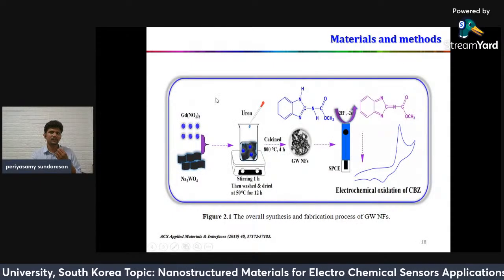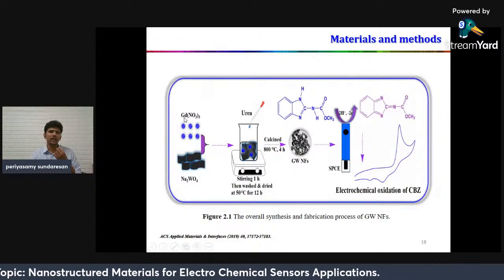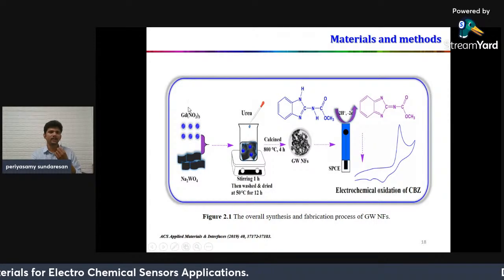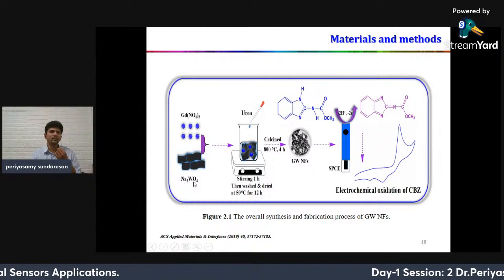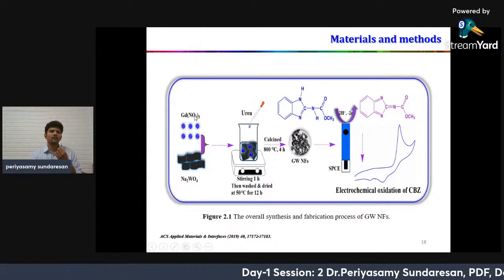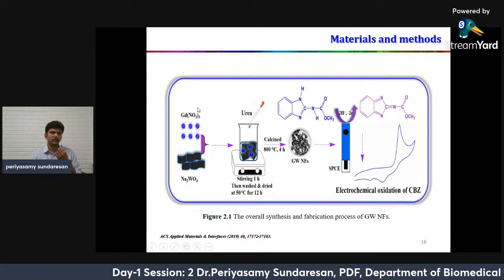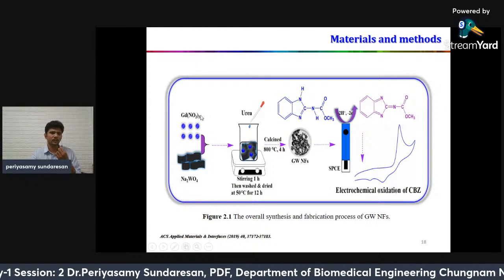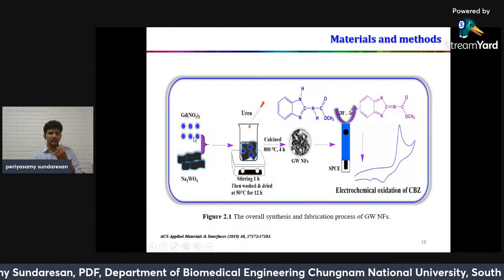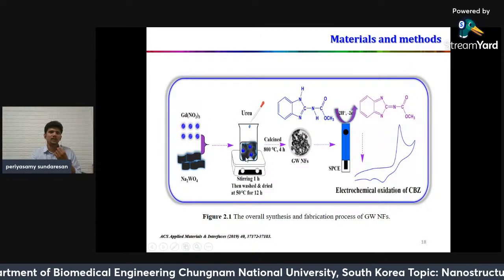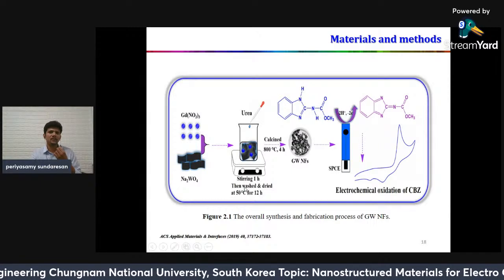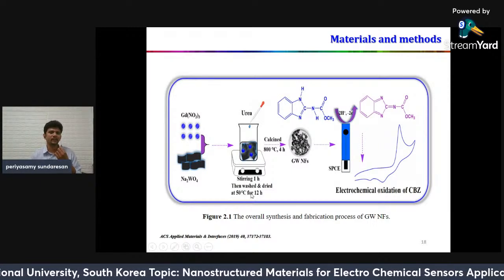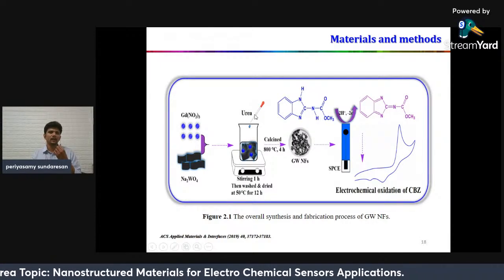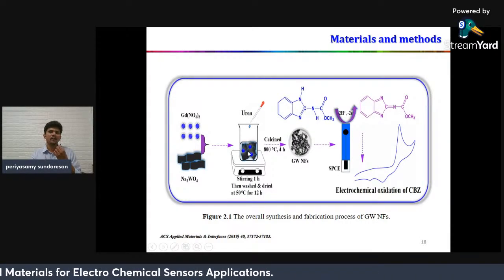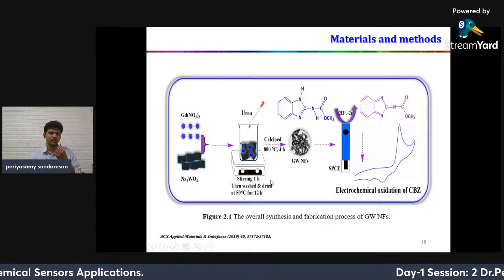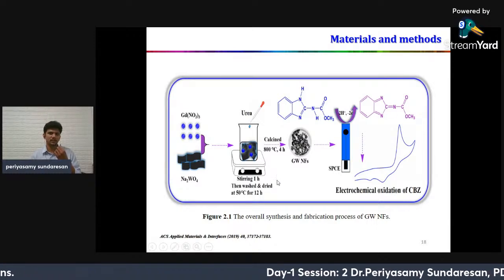This is a material synthesis schematic diagram. Initially, I took gadolinium nitrate, a chemical substance, and a sodium tungstate group. We know very well in our laboratory, it is similar to substances like nickel chloride and copper chloride. This is applied with the co-precipitation method, stirring for 1 hour, in the presence of 50 degrees centigrade for 12 hours. With the addition of urea, I get the gadolinium tungstate group, the ABO3 perovskite tungstate group.